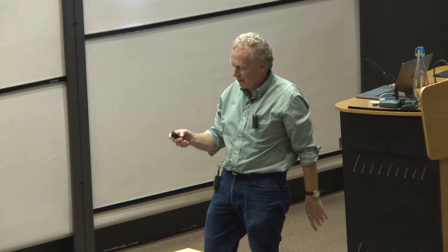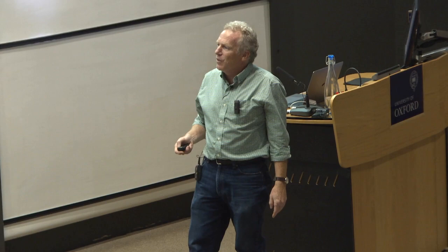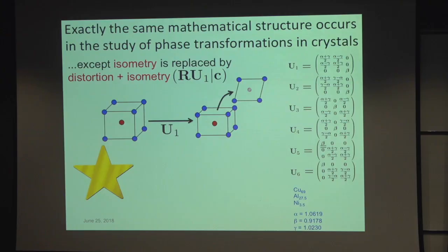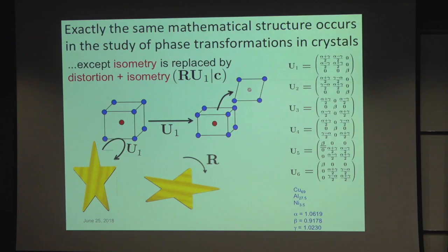Now these are described not exactly like isometries, but quite similar in some way. You first have to distort, doing a linear transformation described by one of those matrices, and then you're allowed to rotate. Of course it's a crystal, so you can rotate it however you want, and it's equally possible before and after rotation. Then you can also have translations. So it's a little bit more complicated than origami. We have not only a rotation or a reflection and a translation, we also have a distortion, but the distortions are discrete. There are only six of them.